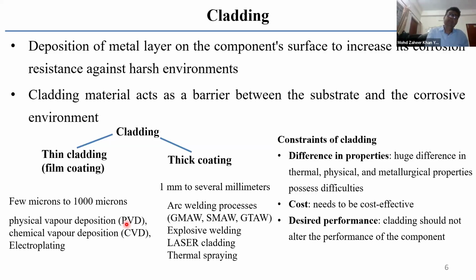And these coatings, being thin, will act as a barrier, but if there is any problem with this thin coating, if it gets peeled out or scratched out, then very easily the underlying material will be exposed and corrosion of this material will take place. So as an alternative, we can also deposit a thick coating, that can range from 1 millimeter in thickness to several millimeters in thickness. For this process of thick cladding, we cannot use physical vapor deposition, chemical vapor deposition, or electroplating as a method because it will be very, very time consuming if you want to develop thick films by these processes. So, arc welding processes, explosive welding process, laser cladding process, and thermal spraying are what is generally used to deposit the thick cladding. There are several constraints when we are performing cladding.